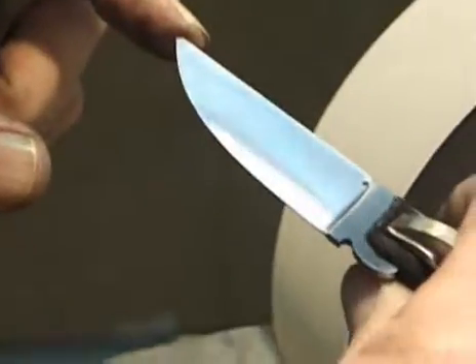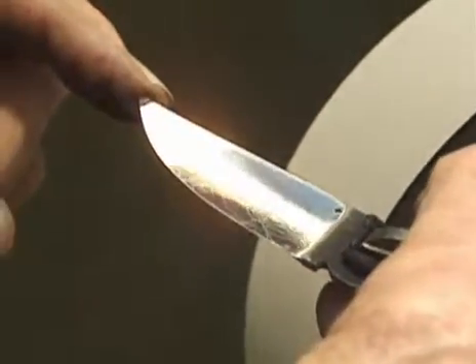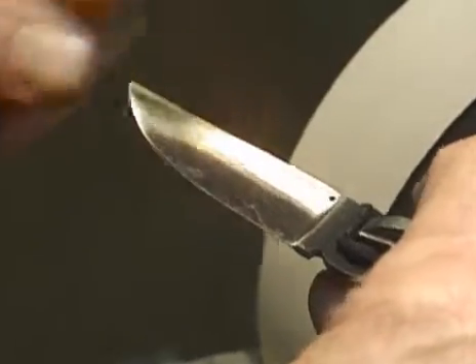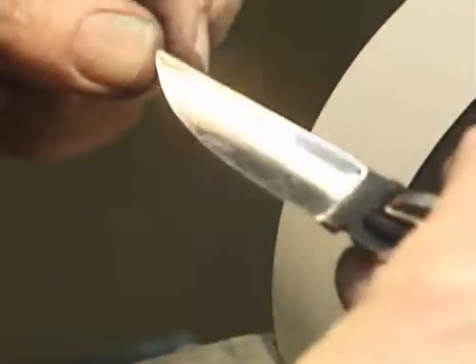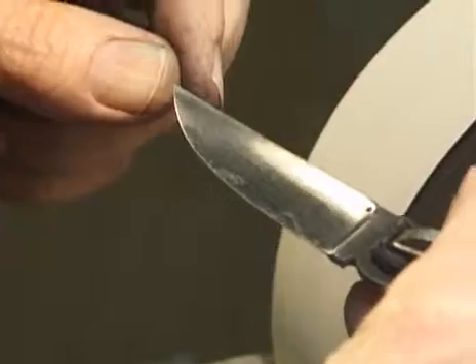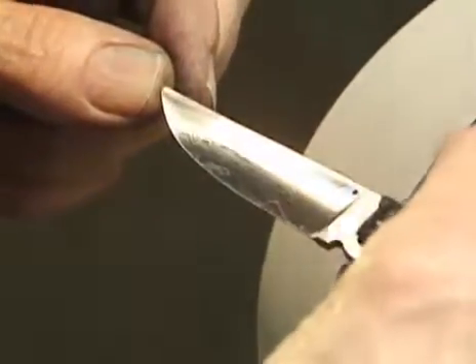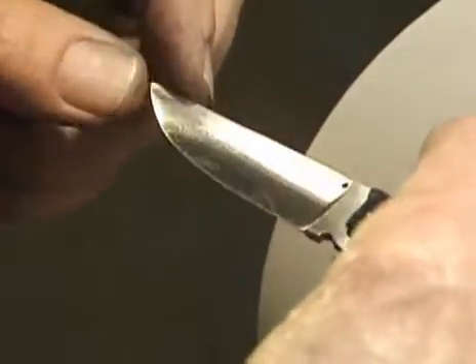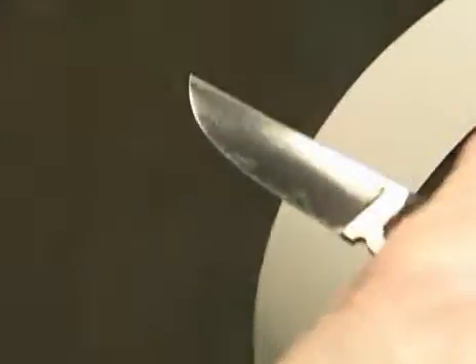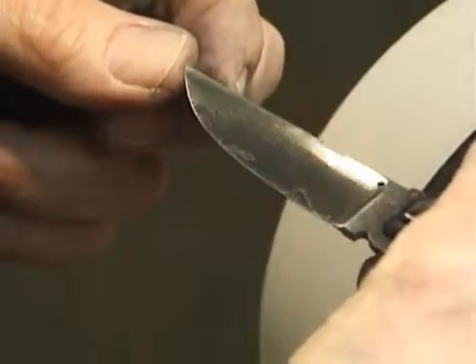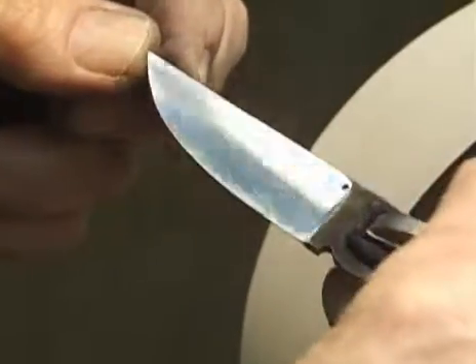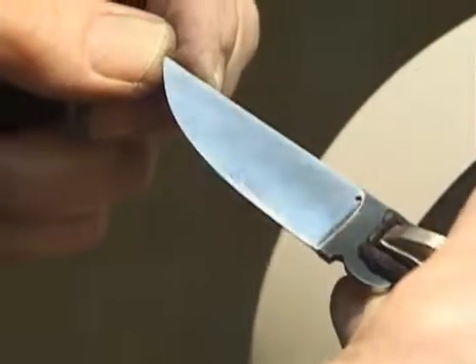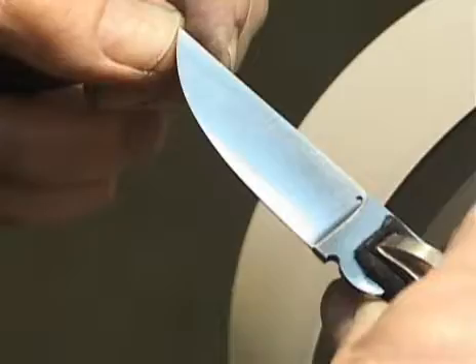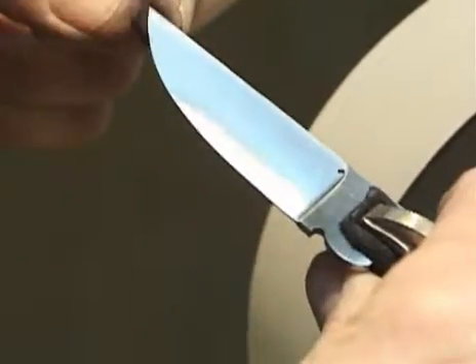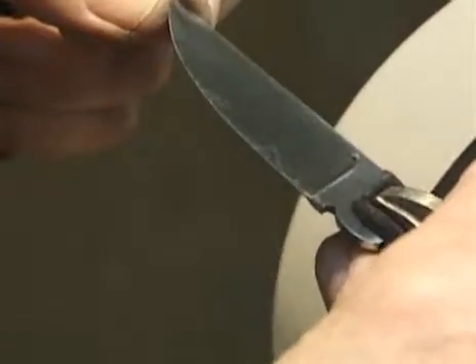Okay, that's a 400 grit finish, and I can go directly to a 600 grit by hand and have a mirror polish on that in just a few short minutes before I etch. Won't be actually mirror polish, but if I were going to buff this, I could go directly to a buffer and put a mirror polish on this blade. But since it's Damascus, I'll do a little light hand sanding and then etch the blade to bring out the pattern. Turned over and do the other side now.